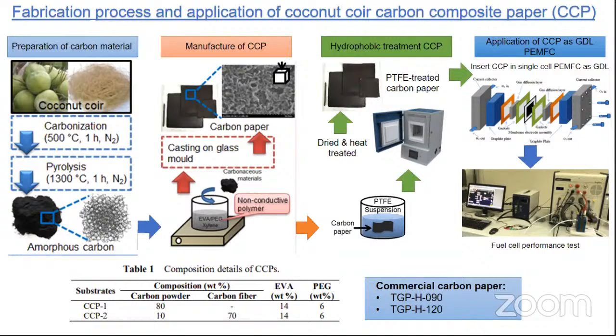For the final product, carbon powder was obtained by grinding and then mesh sieving to a size of about 75 micrometers. And for the carbon fiber process, the coconut coir was first cut to a length of about 2 millimeters before being subjected to carbonization and pyrolysis. And then for the manufacturing step of carbon composite paper, the CCP was prepared by mixing the carbon material with polymer binder to form a slurry. The slurry was then cast on a mold and then dried to form a paper.